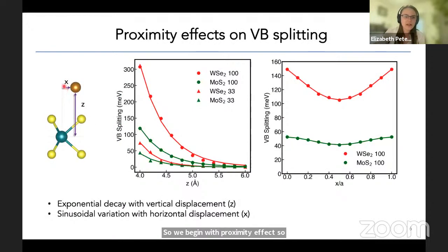So if I place the europium atom directly above the transition metal and move it up and down, what I observe is an exponential decay in the valence band splitting, where tungsten diselenide has larger valence band splitting than molybdenum disulfide. If we zoom in on 4.4 angstroms, which has been shown in prior literature to be the stable separation between surface europium atoms and WSe2 in a europium 111 plus WSe2 heterostructure. At 100% coverage, WSe2 can have a valence band splitting up to 150 millielectron volts, which is enormous. It's an order of magnitude larger than the largest valence band or valley splitting that's been observed. And if we go to 33%, which is maybe a little bit more realistic, we're still looking at about 30 millielectron volts, which is larger also than anything that's been observed.